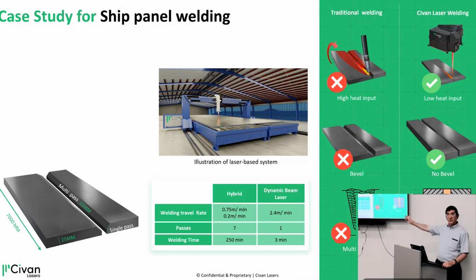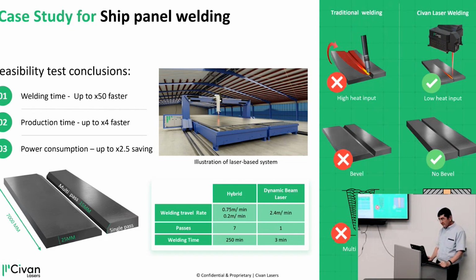Okay, almost 100 times faster. And of course, the heat affected zone is much smaller, and the weld has perfect properties. So it's a huge saving in time, huge saving in energy, and huge saving afterwards in fixing the distortion, because when you put so much heat into the part, you also have distortion that afterwards you have to fix. And here, all this is gone. You just go and it's done.